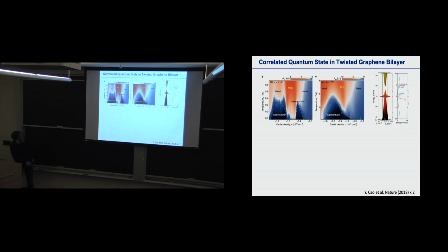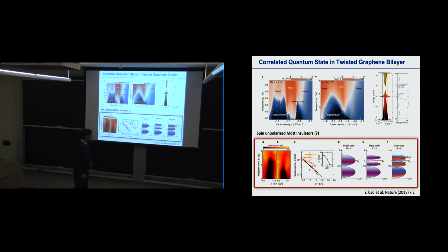At the so-called graphene magic angle, you get this flat band, and that creates gaps, which makes the superconductor. How about the magnetism? What they see in this experiment is that applying an in-plane magnetic field, which only couples with the spin, causes the Mott gap to shrink down and disappear at strong enough magnetic field. The idea is basically that the Mott insulator is spin degenerate—spin up or down—and applying this in-plane magnetic field, due to the Zeeman effect, closes down this Mott gap such that you come out of the insulating state.